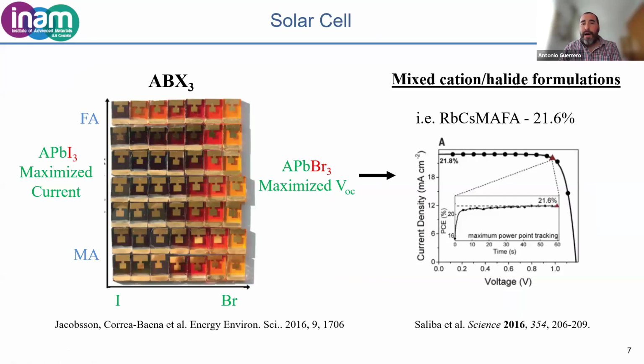So I'm going to show you now some slides about what people have been doing with this type of materials. I quite like this work done by the EPFL group in Switzerland, where they make this very nice matrix of materials with methylammonium as a cation and with formamidinium as well as a cation. And in this axis, they modify the halide from iodide to bromide. As you can see in this matrix, the optical properties, just visually, we can all see that the device turns from dark brown, the methylammonium lead iodide perovskite, to quite orange and yellow when we replace the iodide by bromide.